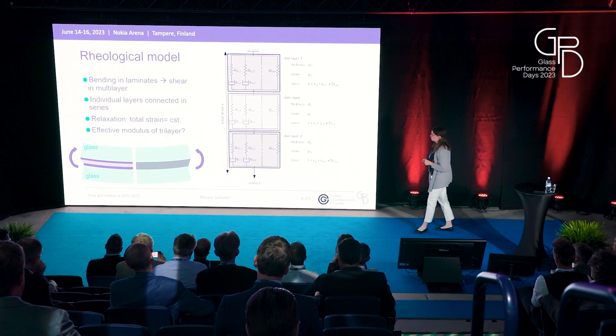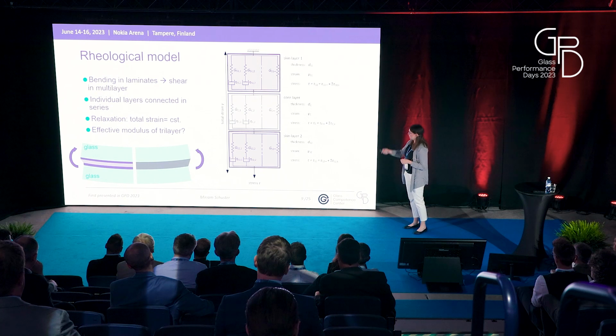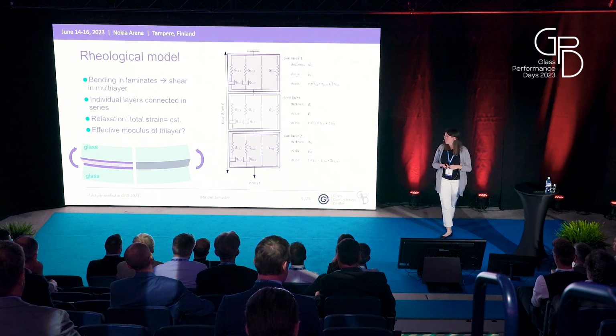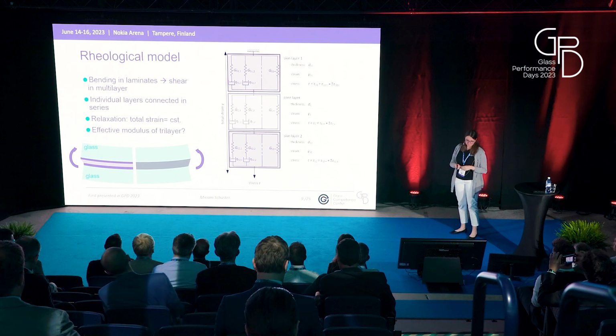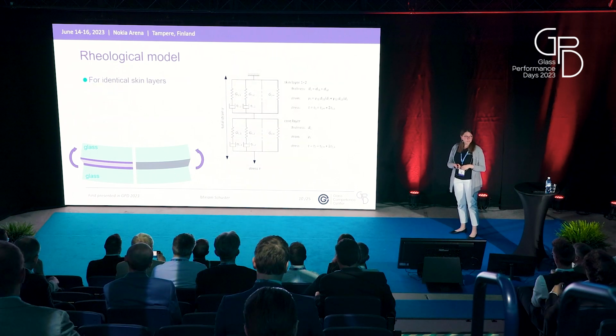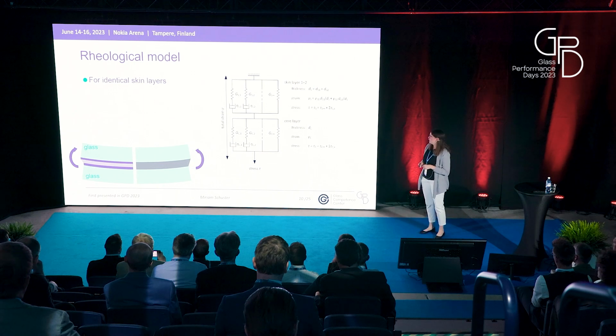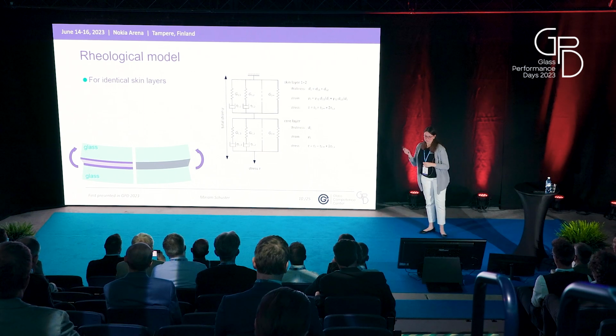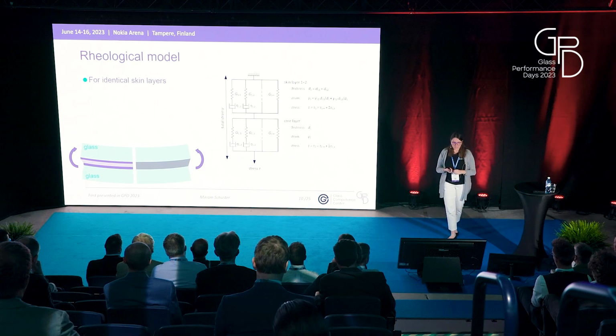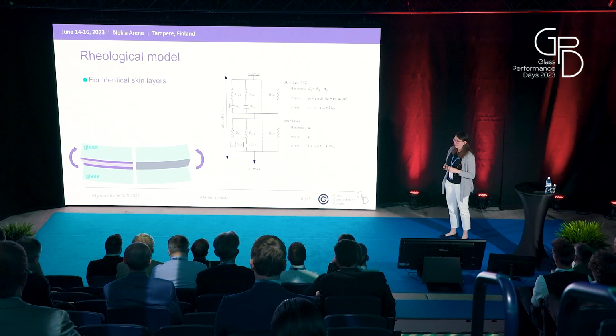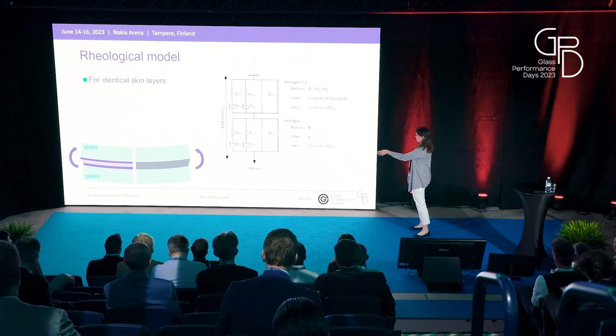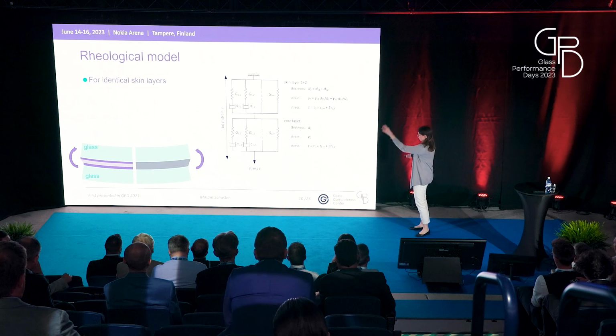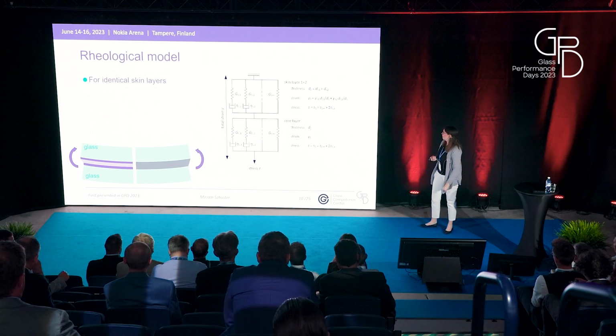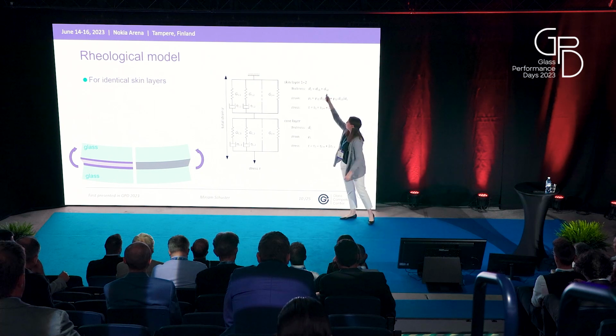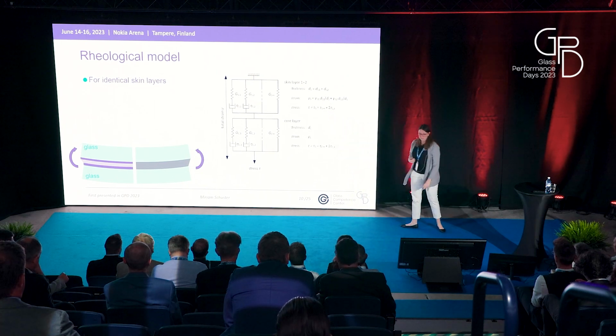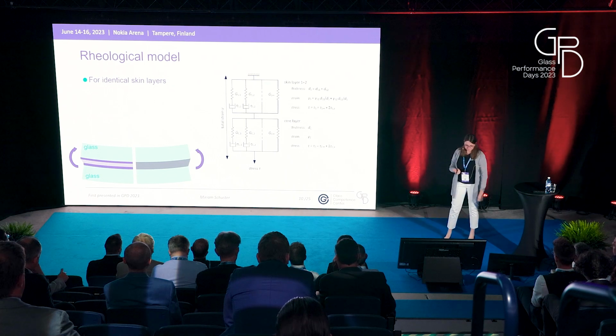And what is of interest would be the response of the combination of those models, and this is called the effective modulus of the 3-layer. As we see, this is a connection in series, which means that we can change the order of the connection of the individual layers. And when we have identical skin layers, we could move the 3rd generalized model, which was depicted in the slide before, just to the first one and combine them, respecting a total thickness for the skin layer. So this makes it already easier for the calculation.